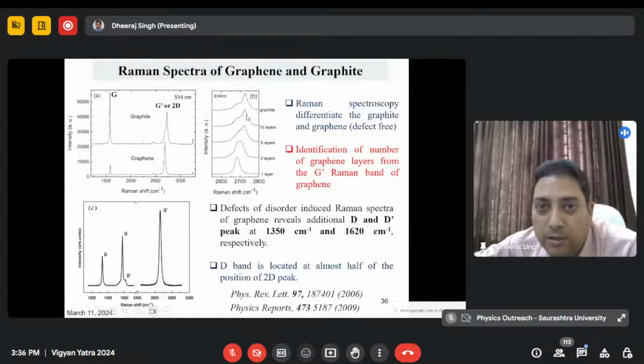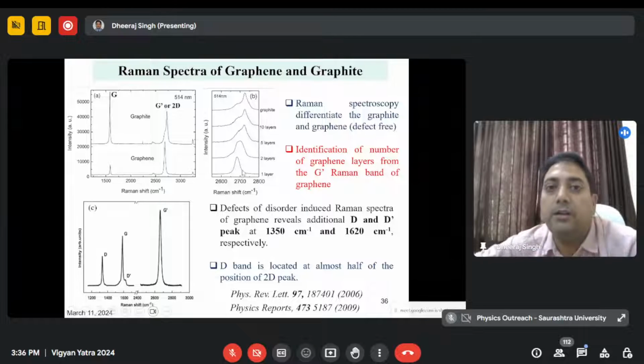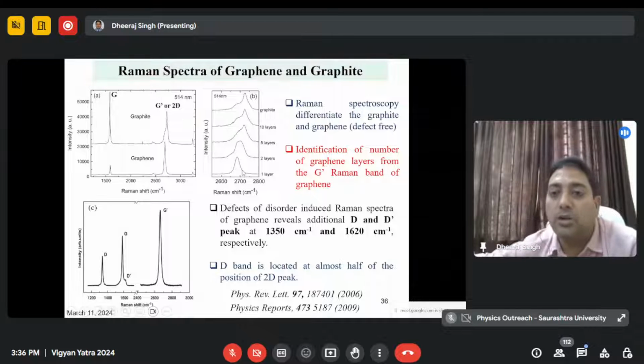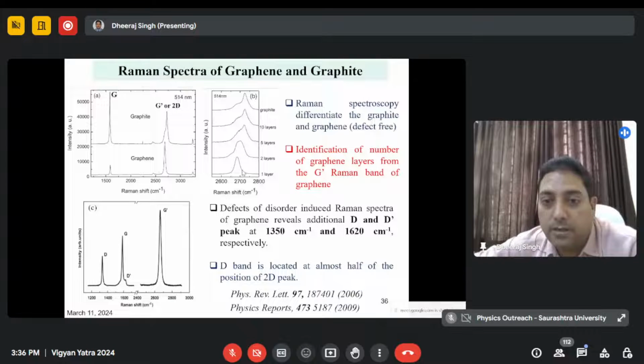Now in this spectra, we can see this is the Raman spectra of graphite, but in the Raman spectra of 1 layer, 2 layer, 3 layer graphene, we can see that it is red shifted, because you know red shifted means that the frequency is changing. So any defect, now we are interested in making a defect, any defects in your sample can give an extra peak known as the D band. D band means disorder or defect band.